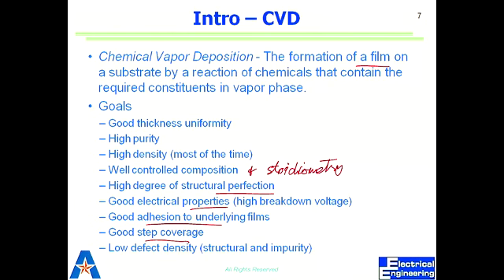Now, there's another factor from the outcomes that you want. We may want it to be doped. So our outcome may be heavily doped polysilicon, because it's going to act as a metal, and it's going to act as a gate. Or we may not want it to be doped. So we can do what is called in situ doping. From our recipe, we can get heavily doped polysilicon. Or we can do doping by conventional way. How do we do doping? Diffusion, right? Or implantation. But we can do it in situ as well while we are doing that. So it may be whatever electrical property, conductive, insulator, whatever you want.